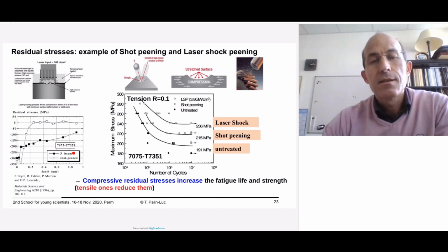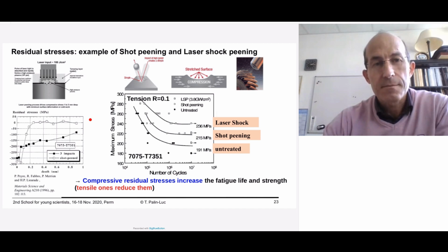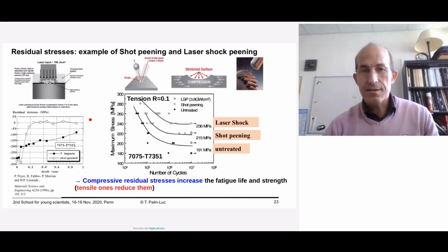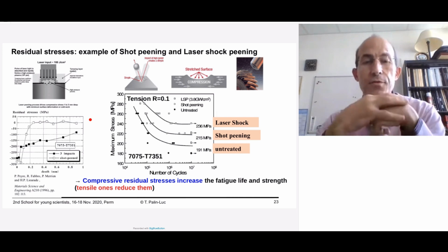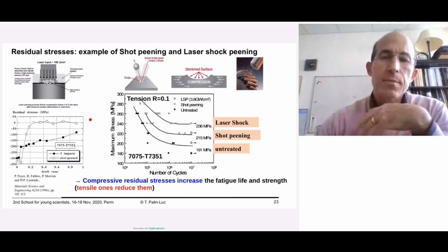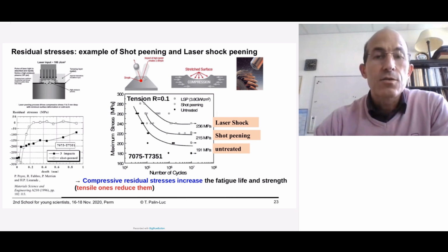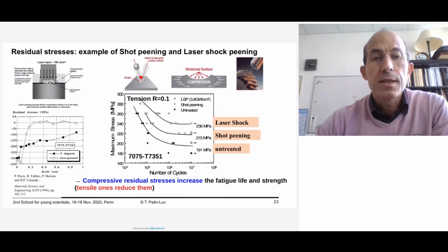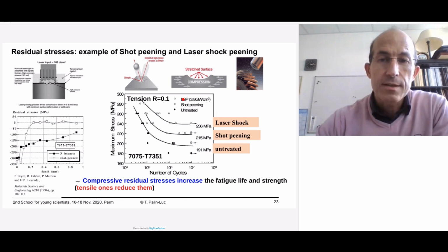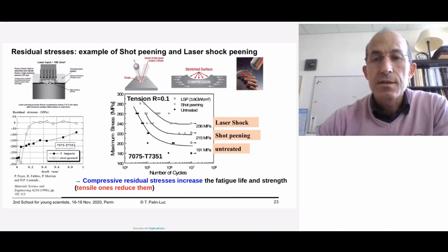Another important factor in real components are the residual stresses. The residual stresses are the stress inside the material without external loading. So of course, the residual stresses are in equilibrium, but they are produced by external loading in order to reinforce or to modify the surface layer of the material or the components. A typical treatment is shot peening. Shot peening produces plasticity at the surface, and the plastic region is compressed by the rest of the material surrounding this area. The elastic material compresses the plastic zone. So this treatment is very well used in industry, for instance, in order to increase the fatigue resistance of gears.